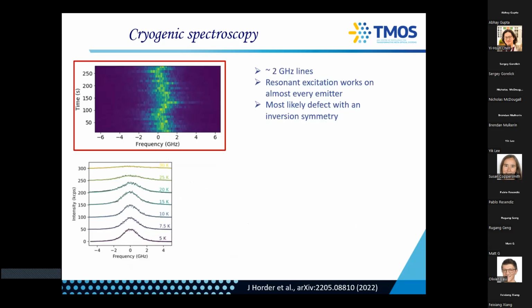And of course, if you then cool it down and you bring your narrowband laser exactly to 436 and you start scanning to see what the line width is, you get 2 gigahertz. So it's very good because it's 2 gigahertz stable. You see the repetition here. You scan again and again, and you always get the same line. The emitter doesn't disappear, no fluctuating fields, basically happy days. This is just as a function of temperature to get the phonon replica.